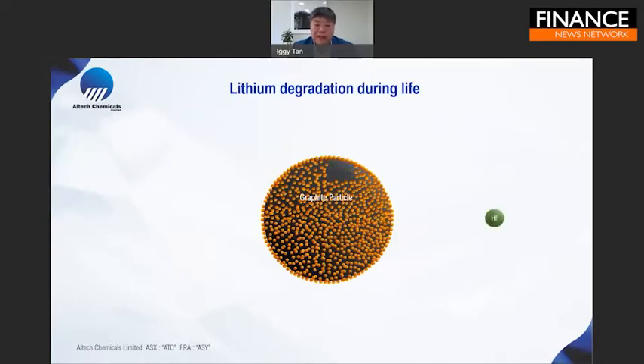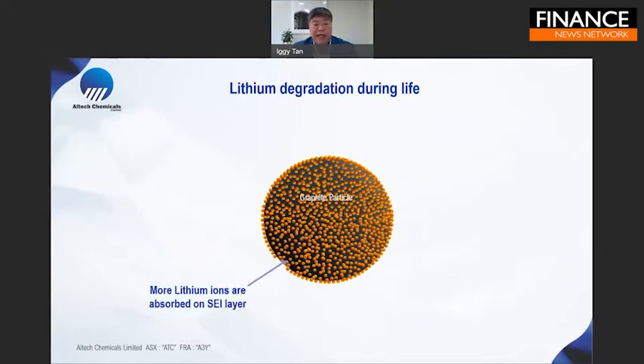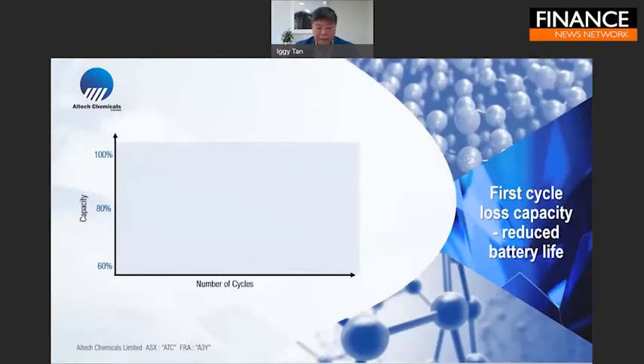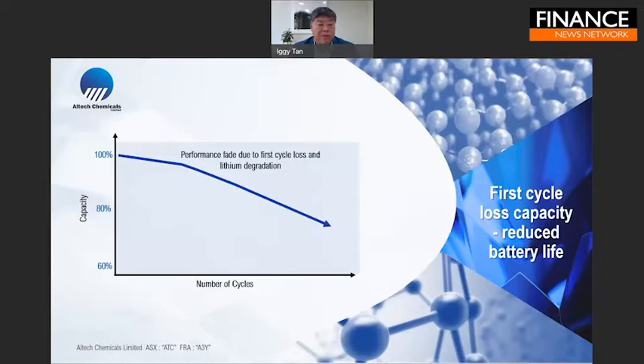The other thing is that hydrofluoric ions in the electrolyte break down the SEI layer. As it breaks down the SEI layer, more lithium is absorbed. So there's a constant degradation of lithium in the performance of the battery. And if you look at a battery curve, this is what the curve looks like. It drops away from 100%, and at the 80% mark, that's the life of the battery.